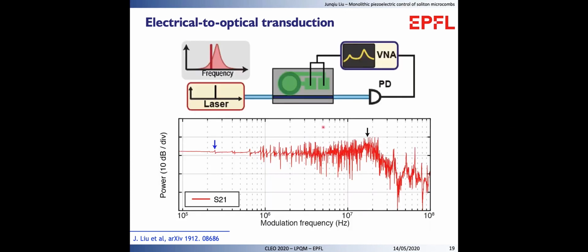We further characterize the electro-optical transduction using the setup shown here. A vector network analyzer applies the sweeping frequency driving on the aluminum nitride actuator. The laser is tuned to the slope of the resonance. By modulating the aluminum nitride, the transmission changes correspondingly, which allows us to measure the electro-optical transduction as shown here. There are many peaks observed which have the profile of acoustic resonances as I showed in the previous slide.